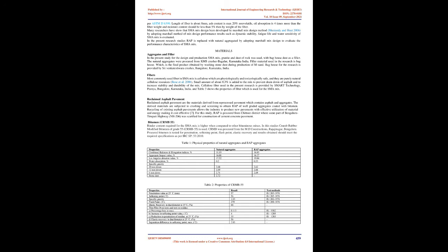SMA application has been carried out mainly on high-volume roads as a high-resistance and highly durable layer which helps in noise reduction and light reflection during the rainy season. A typical SMA mix consists of 70% coarse aggregates on or above the 2.36 mm sieve, and filler in SMA is about 10% of weight of mix passing the 0.075 mm sieve, Dong and Tan 2011. Cellulose fiber of about 0.3% of weight is added to prevent drain down. If fibers are not added to the mix, it will lead to formation of fat patches on the pavement surface, Michael et al. 2003.